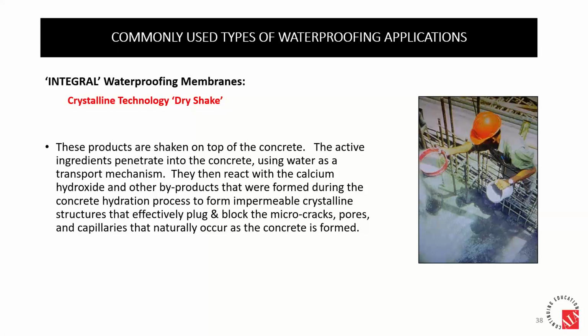This is the same material. This is a different way to apply it. In this case, they have freshly poured concrete. So that concrete is still full of water, still wet. And they're shaking the crystalline on the surface. You can see in the picture, just like confectionery sugar in a bakery. And the crystals react with that water, and that causes it to penetrate into the concrete and form those crystals. Again, blocking micro cracks, pores, capillaries, any little opening within that concrete.